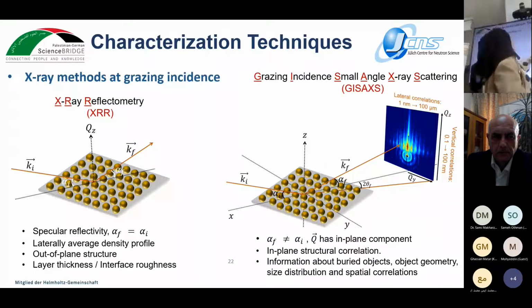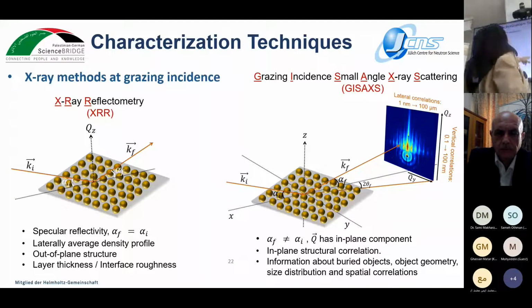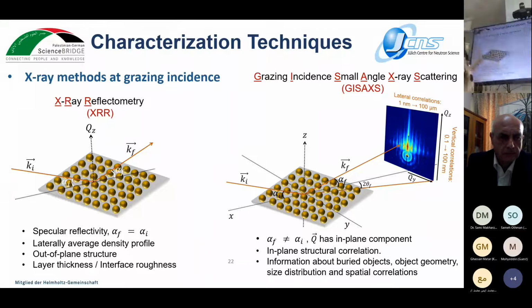The Z-axis is the normal to the surface, while the X-axis is parallel to the direct beam, and the Y-axis is the perpendicular one. So, in X-ray reflectometry, the scattered angle equals the incident angle, and it gives us information about the average density profile, the out-of-plane structure, the layer thickness, and interface roughness.